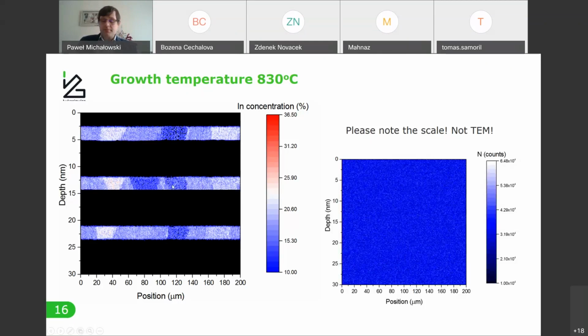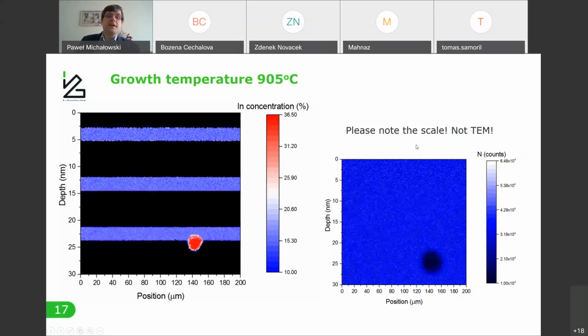At the same time, I made the additional analysis of nitrogen distribution in the same region, and for this temperature you can see that there is absolutely nothing interesting, a homogeneous distribution. However, when we increase the temperature, we see the homogenization of this indium distribution within these quantum wells, and that's why the quality of the optical power was much higher and the wavelength emission much better controlled. However, we see that from the bottom layer, the first one which was grown, there is some kind of indium precipitation, which is also noted by the corresponding decrease of nitrogen in here. So we can expect to see some metallic indium starting to precipitate from this region. There are not so many regions where such precipitations can be found at this temperature. That's why the operation at this temperature was very good.